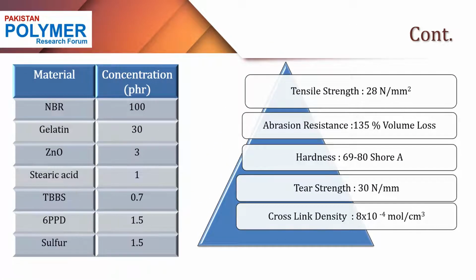For my research proposal, I have displayed one of the reference recipes here, being the combination of rubber, cross-linking agent, filler, activator and accelerator. In this you can see I have added 100 phr of NBR, then the filler, that is the gelatin, is 30 phr. ZnO, stearic acid, TBBS are the accelerators and activators, added from 0.7 to 3 phr, and sulfur being the curing agent added in this formulation.